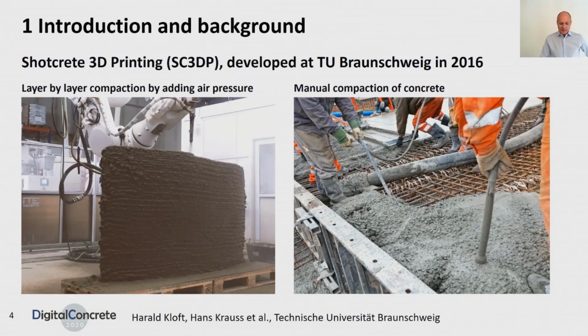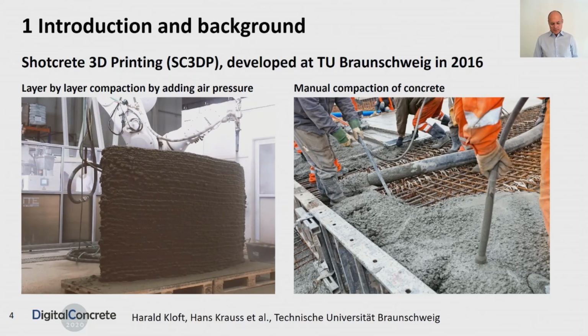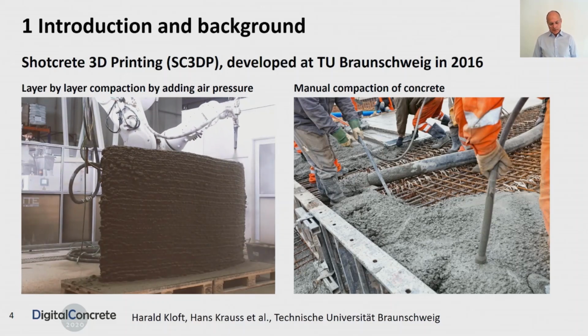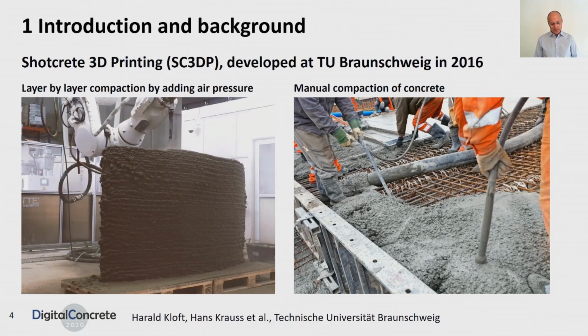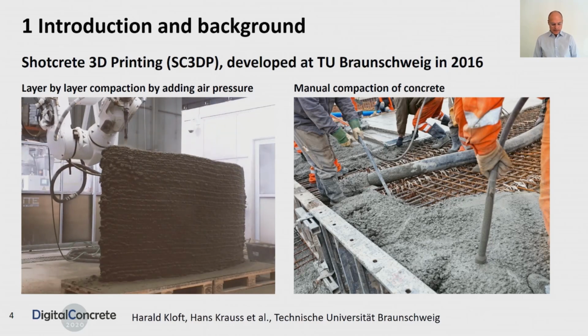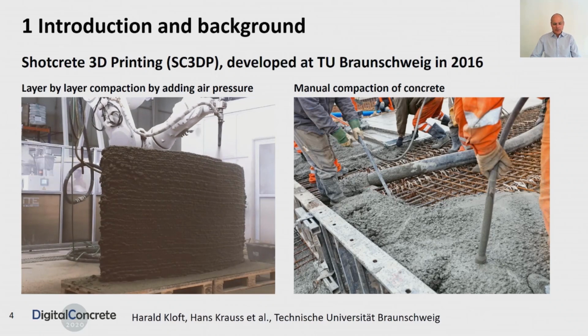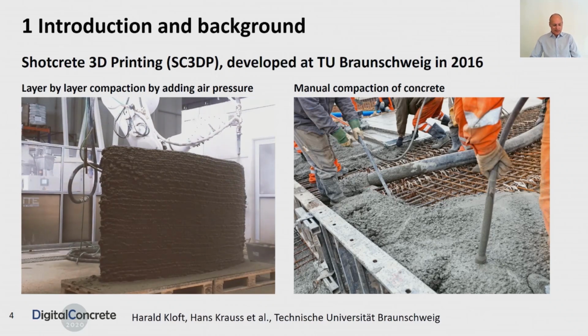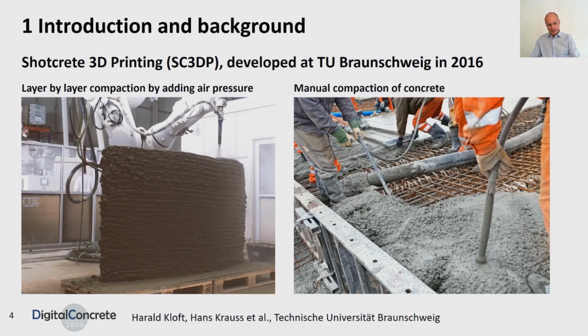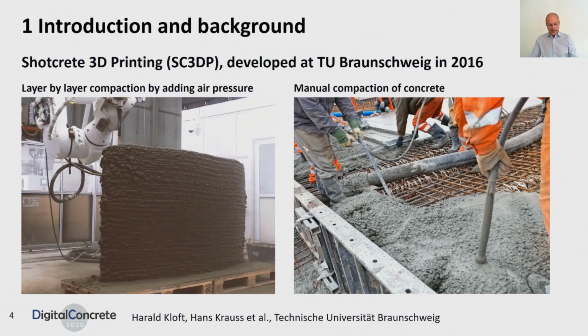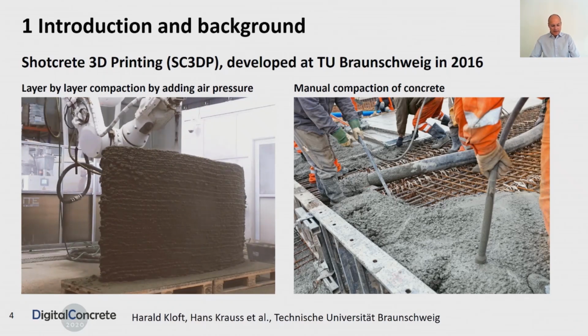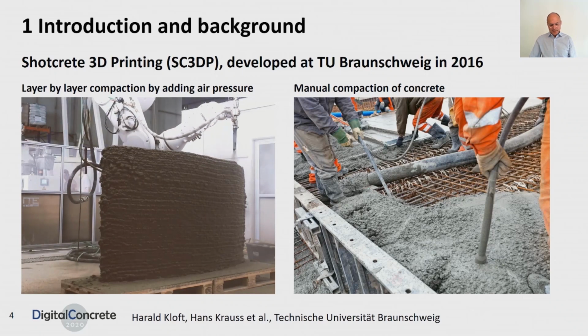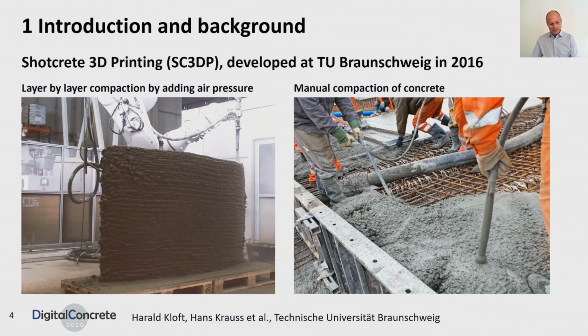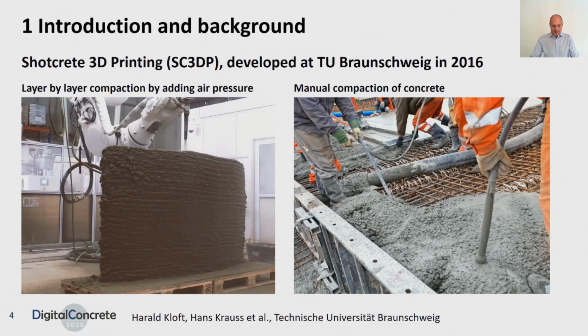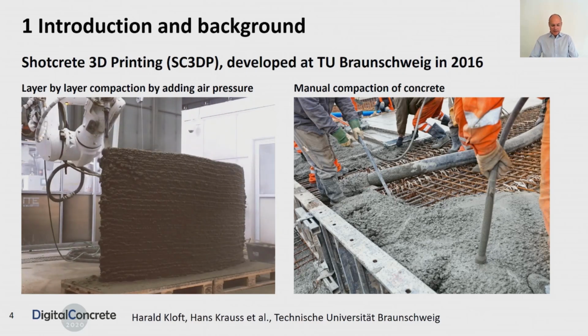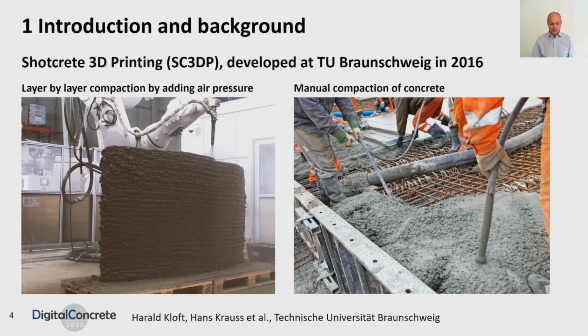The results of the investigations presented today are based on a 3D printing process for concrete components developed at the TU Braunschweig in 2016. The special feature is that the concrete matrix is accelerated by adding air shortly before the nozzle exit. This acceleration of the material creates a kind of layer-by-layer compaction. In contrast to compaction by concrete vibrators, this can of course not be described as homogeneous.